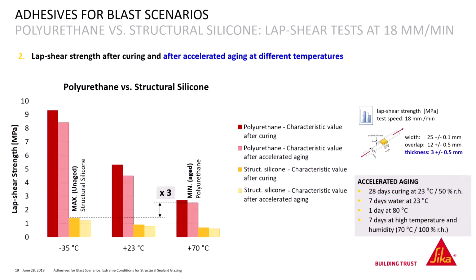When we go to 3 millimeter thickness and do more comparison at various temperatures, minus 35 degrees, plus 70 degrees, and we also compare the worst case for the polyurethane with the best case for the silicone, it's still a factor of 3 where the polyurethane outperforms the silicone. Okay?